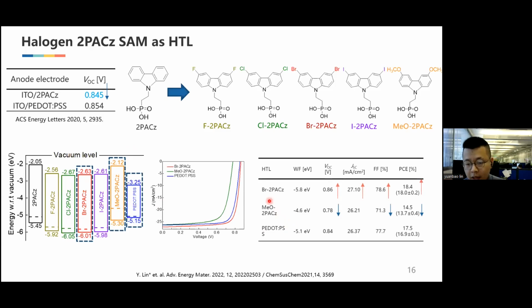As we can see, the MeO-2PACz, due to the lower work function, has a VOC that is reduced a lot as compared to PEDOT. But for the bromide 2PACz, the VOC is better than the PEDOT. Finally, you can get a higher performance without sacrificing the VOC, and also maintaining the JSC and fill factor.